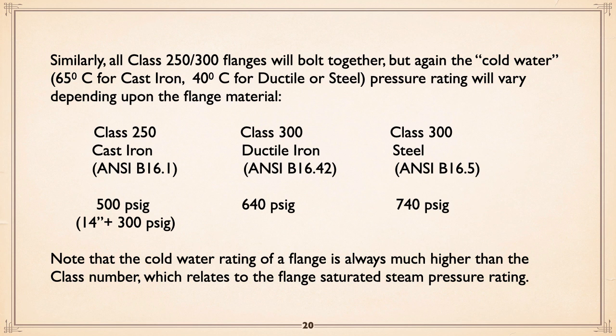Similarly, all class 250 or 300 flanges will bolt together. But again, the cold water rating will vary depending on the flange material. In class 250 gray iron, B16.1, 500 psi, 14 inch and above 300 psi, class 300 ductile 640 psi, class 300 steel 740 psi. Note that the cold water rating of a flange is always much higher than the class number, which relates to the flange saturated steam pressure rating.